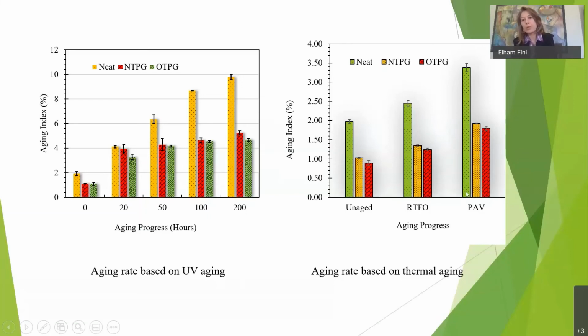So imagine an old road. This one, the first bar, is the current Arizona asphalt. The second two bars are the ones that have plastics, with the red being the one that we treated, so the oil-treated one. The aging difference, just look at this PAV, which is representing an old road, let's say a road at the end of its life. You can see the amount of aging difference if you have the plastic and if you don't. So imagine how old this one is compared to this? Almost twice. If I want to exaggerate on the numbers, there is no one-to-one correlation. But if this green represents a 30-year-old road, I would say that the red is like half of that age. So it's much younger, even though they went through the same aging.